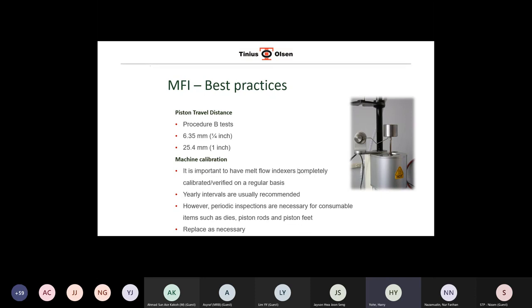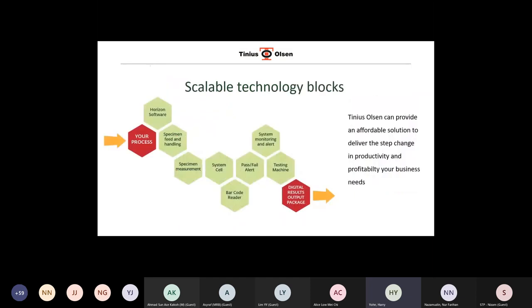Some people clean their machines with some sort of solvent — we don't necessarily recommend that. We prefer the manual techniques — brass brushes and cotton cleaning patches. The reason we don't like solvents is because we've seen cases where solvents affect the results in the testing that follows — it can either speed it up or slow it down from the expected rate. In 30 years, I've seen anything from water to floor wax stripper used on components through the die or melt indexer, but we don't recommend it. That's pretty much what I have. We make other machines besides the melt flow — tensile machines, IZOD and Charpy machines. We try to stay in contact with all our customers through the ASTM and ISO process.